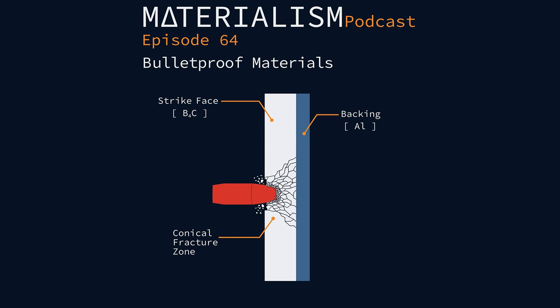And speaking of fracture, the other thing you have to understand about having that metal backing plate, something I talked about in the science around that Batman thing that I'd never thought about before, is that once that ceramic fractures, that's a bullet now, because that ceramic is basically going at high speeds towards you in sharp edges. Yeah, that leads us to the next configuration you'll see. Because if the ceramic is great at eroding the material, you might think, well, we should have a thicker ceramic as well. But because of that high velocity as well as the high stresses, you'll just get ejection of the ceramic. And it's going to go one way. It's going to go either more or less into you, or out.